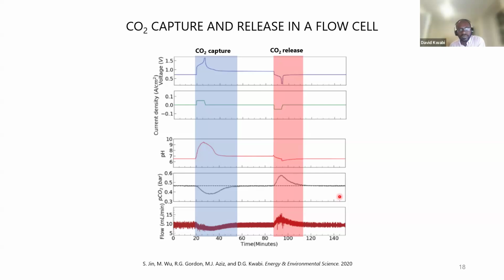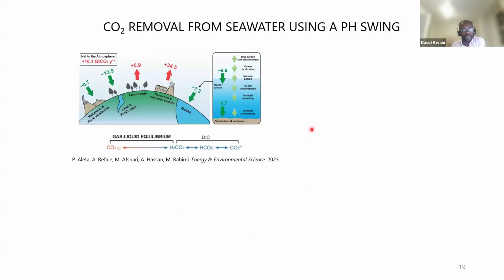But what we've become more interested in lately is this idea, not just of capturing CO2 from flue gas or air, which turns out to be very challenging, but actually releasing CO2 from seawater. You might know that we release on the order of 20 gigatons of CO2 per year into the atmosphere, and the oceans absorb about 1/4 of the CO2 that we emit annually. That CO2 exists mostly as bicarbonate, but if you can reversibly acidify that seawater, you can turn it into CO2, capture that CO2, return the seawater to the ocean, and then use the ocean to passively draw down more CO2 from the atmosphere. So removing CO2 from seawater can be an indirect way of mitigating our atmospheric CO2 levels.